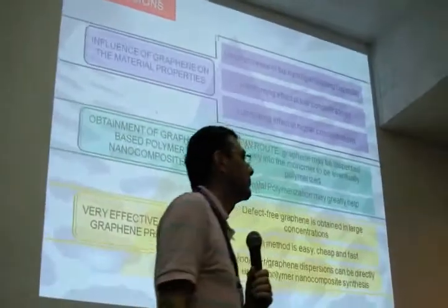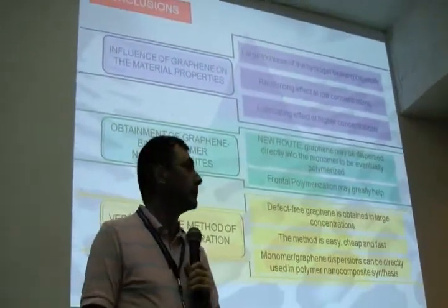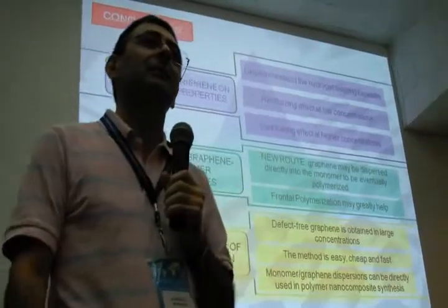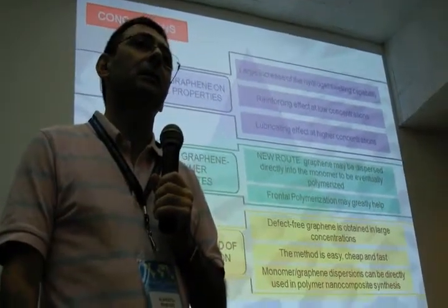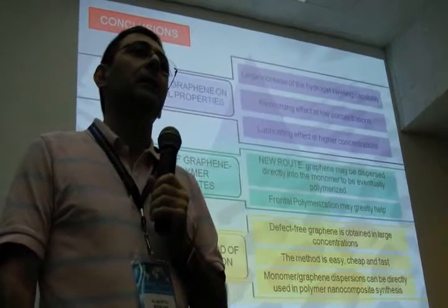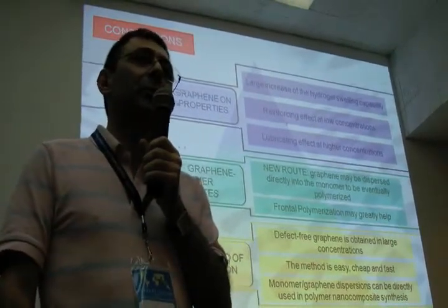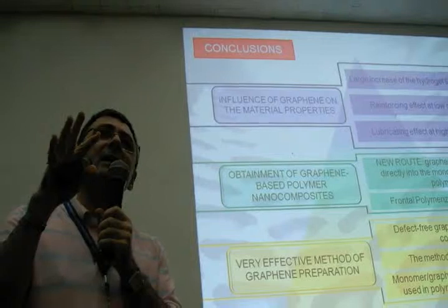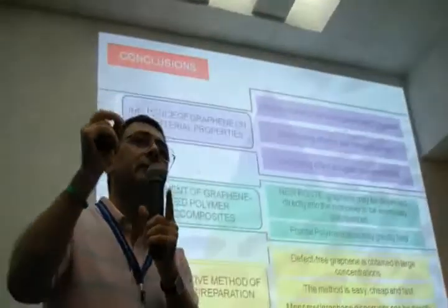We have time for a few questions. Have you tried to use any oligoethylene glycol monoacrylate or methacrylate as a dispersing agent? Yes, we use. I think that the system you are mentioning is probably the best. The presence of some oxygen in relatively long, low molecular weight molecules seems to be the best. So oligo systems seem to work well.